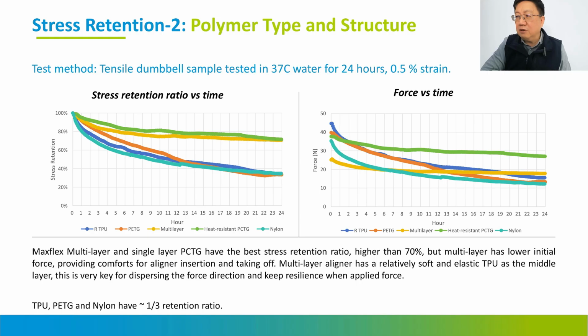In China, they have this kind of regulation based on 24 hours and 0.5% strain, in 37°C water, to see how they change. So Maxflex, the multi-layer compared with a single layer, has the best stress retention, more than 70% stress retention. But if others, you can see they lost a lot, and so it gives you another idea.